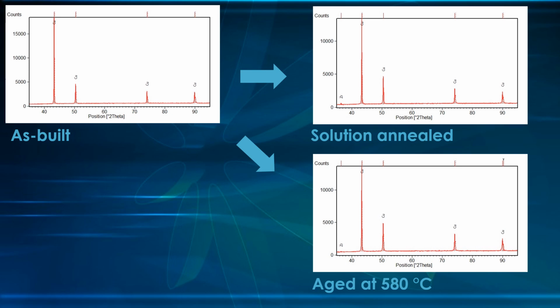So this suggests that after the production process, in the as-built specimen, because of the very high cooling rates during the additive manufacturing process, we have the formation of a supersaturated solution, while after solution annealing performed at high temperature, we produce diffusion of different elements and precipitation of zirconium and chromium rich phases. So in that way, zirconium and chromium are not available for forming the small nanoprecipitates, which are the ones that can effectively hinder the dislocation motion and increase the mechanical properties of the alloy.